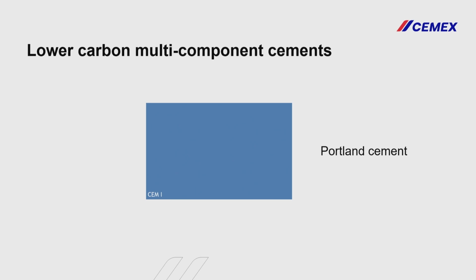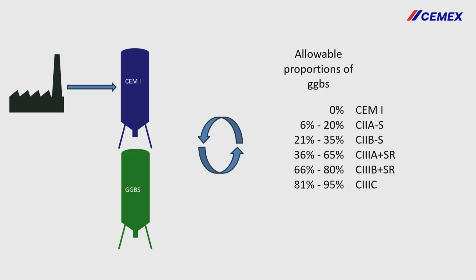Let's say pre-November 2023, not strictly true, but we'll use that as an example. We take a Portland cement, and we then used to add GGBS, typically from 10, 15%, all the way up to 95% if we think about some of our geotechnical works. And that is a binary cement. What the changes to BS 8500 in 2023 allowed us to do was to add limestone fines to BS 7979, okay? To become a ternary cement. So again, it's probably terminology that you've all heard.